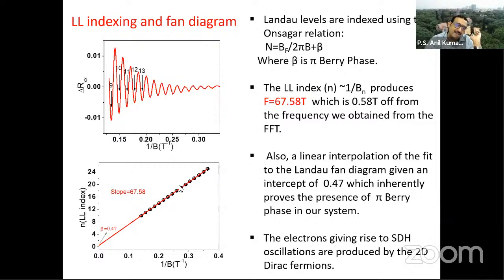Now, if you extrapolate this, you see that this is giving you an intercept of 0.47, and this 0.5. If the intercept is 0.5, then it tells that you have a pi Berry phase. So this also tells you that you have a pi Berry phase in the system. So all this data gives you information that it is 2D Dirac fermions in the system. So this is the first time that in a weak topological insulator, we are getting such kind of information.